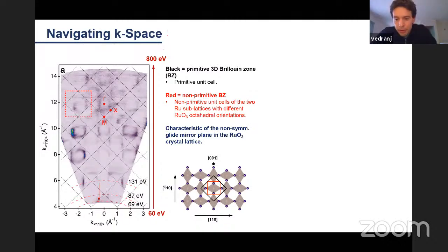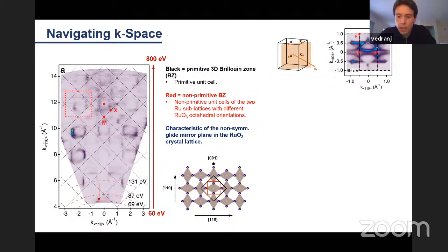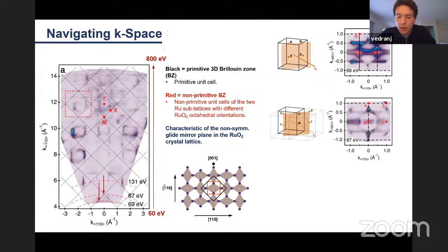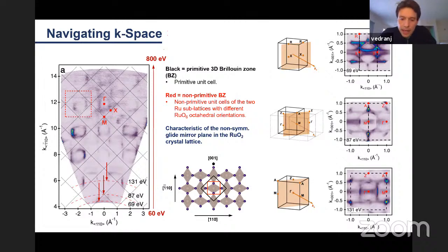So from this periodicity along the 110 planes, we can identify photon energies at which the ARPES probing sphere cuts the Brillouin zone close to the high symmetry planes. And I showed this in the image on the left. And at these energies, we essentially acquire ARPES surface data sets using the system. And so as illustrated here in the top of panel B, the ARPES hemisphere at 69, you can see where it cuts, and it produces this Fermi surface that contains both the X and R high symmetry points.